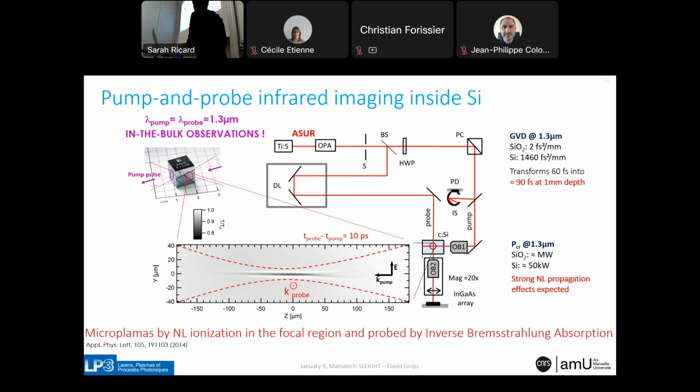So in practice, we take our femtosecond laser, we split it in 2 parts. One is a probe, delayed in time. You have a delay line that you can adjust so that you can illuminate the sample at different times. While you irradiate, you focus the light inside it, and you observe this with a transmission infrared microscopy imaging system. This will give you this type of snapshots.